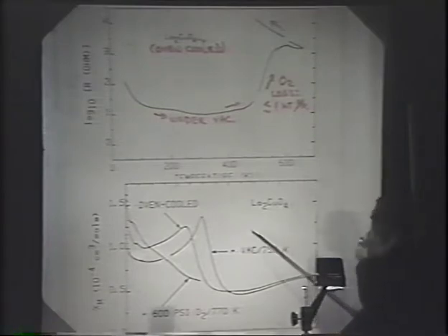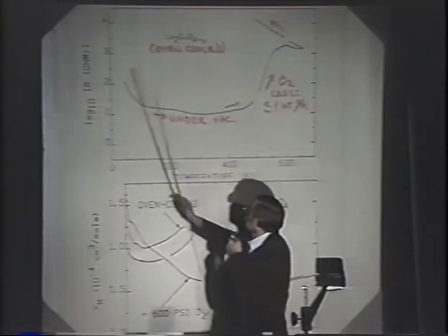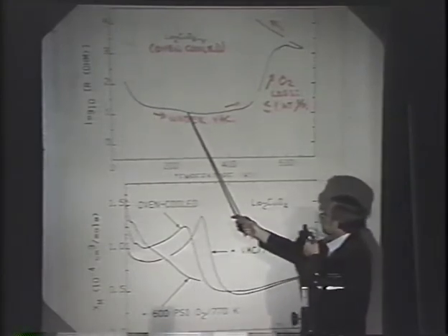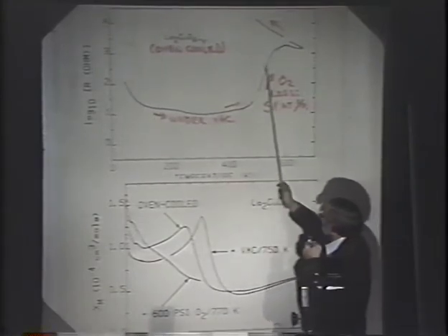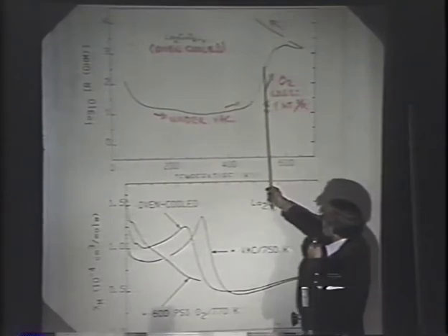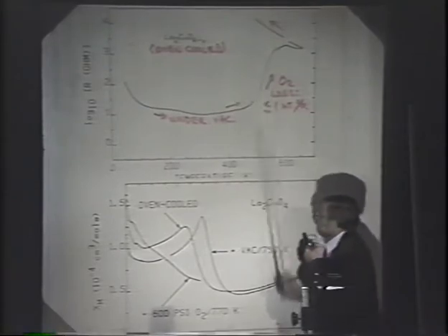A couple of things. You've heard about the localization at low temperatures. There is an inflection point here. This is the temperature of the orthorhombic to tetragonal phase transition.